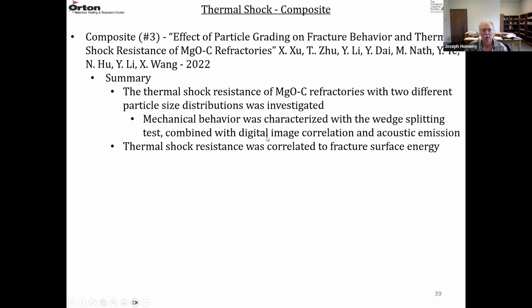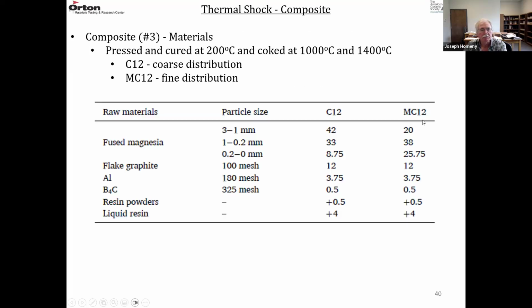But they also added a digital image of the fracture pattern, and they added acoustic emission. So they try to characterize in more detail the fracture behavior. And they correlated the thermal shock resistance to the fracture surface energy from the wedge splitting test. So they had 2 compositions, the C12 and an MC12. The C12 was the coarser distribution, the MC12 was the finer grain size distribution.